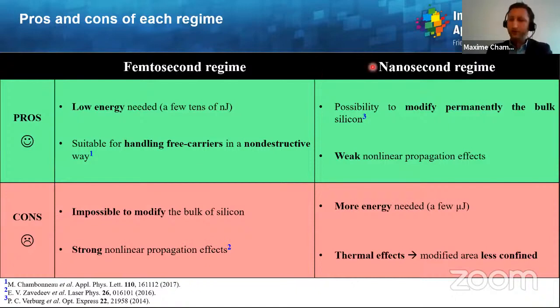But then if you go to the nanosecond regime, so 1 billionth of a second, then it has been shown that it is possible to modify permanently the bulk of silicon. This is due to the fact that when you increase the pulse duration, you decrease the intensity, and thus you decrease the nonlinearities inside the material. However, of course, more energy will be needed, and the main drawback is that, as I said in the introduction, you cannot separate the causes and the consequences, and thermal effects will occur during the pulse, which will lead to a high heat affected zone.